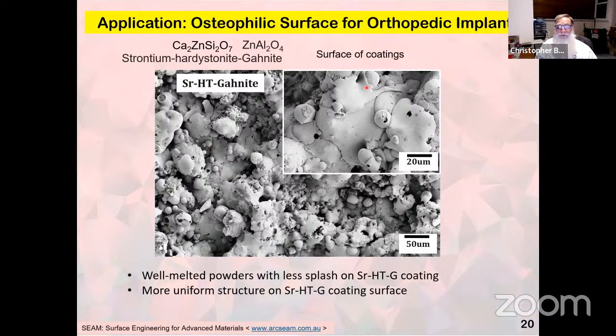And you can see the degree of melting. You start counting splats. You can see porosity. You can see these little satellites or fine particles. And this is where the taxonomy, remember I keep on talking about particle size distributions. This is where measurement of what is happening at the substrate can give you hard numerical data on how you can control the power, the voltage and the current, standoff distance, all those parameters, so you get a different character.